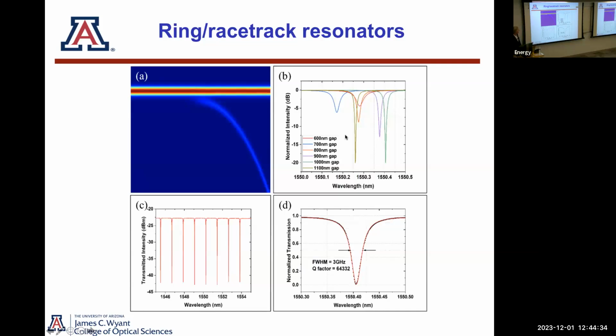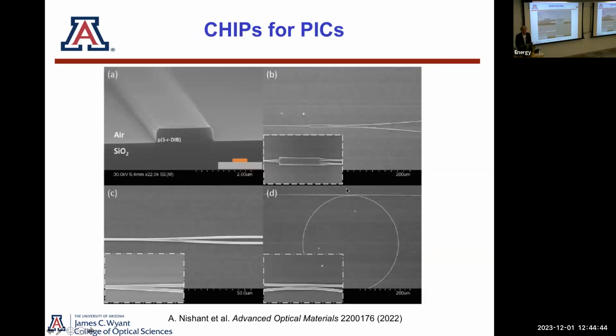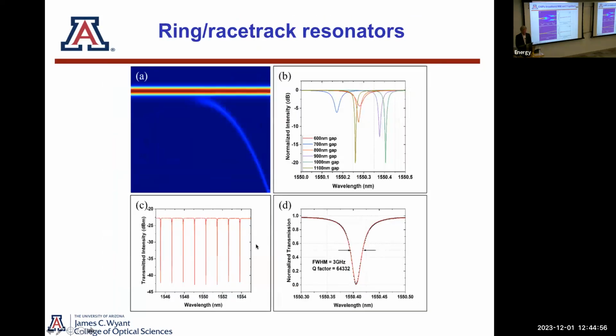And here we show a ring resonator that actually works quite well. This is simulation up top. This gap, if we look at here, I have this little gap between the ring and the waveguide. This is where the light actually couples from the multicolored stream to one color sitting on the ring. And here I've got that one color sitting on the ring, and this is looking at the sensitivity to that gap. So your lithography has to be able to control that gap size, in this case, from 600 nanometers to about 1100 nanometers, which is doable.